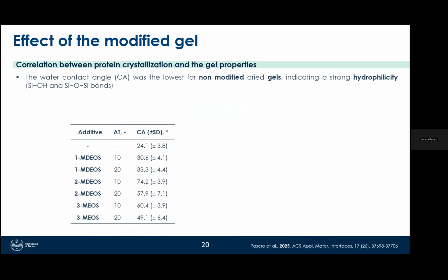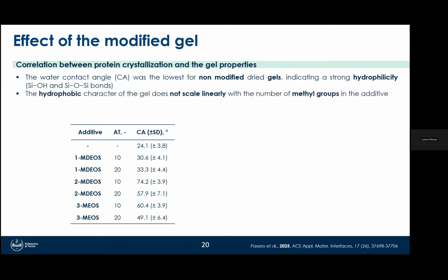gel properties. So in the final parts, we started with contact angle measurements to evaluate the hydrophobicity of these gels. And we looked at the contact angle measurements, and we saw that the contact angle was the lowest for non-modified dry gels, indicating a strong hydrophilicity, while the hydrophobic nature of the gels increased with the methylation, but it did not scale linearly with the number of methyl groups, which is coherent with the phenomenon observed before, since we see here that the contact angle is not increasing anymore when 3 methyl groups are introduced.